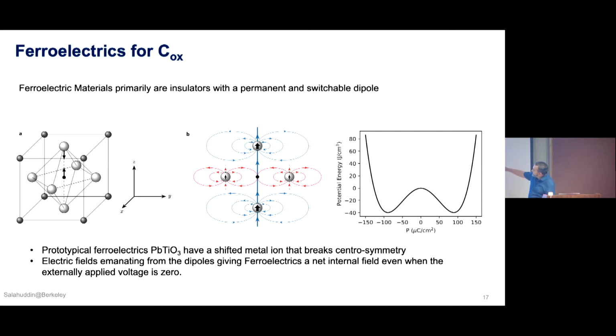What it has is that in its unit cells, there are dipoles. What that means is that there is a metal atom which is slightly shifted from the center of the unit cell. If the metal atom is slightly shifted, it creates an electric field. So now you can imagine that you have all these unit cells all over your material, each one with an electric field. They start to interact with each other, and this interaction stores some energy. That stored energy provides us with this middle part. It would have been a parabola, like a standard dielectric, but this stored energy gives us the middle part, thereby giving us a W-looking energy landscape.